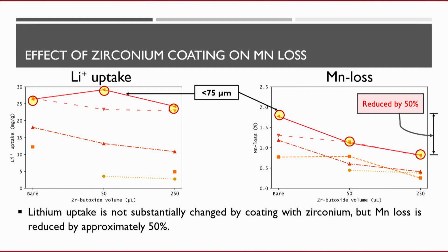Starting on the left, you can see the lithium uptake there, and there are three columns. There's the bare sorbent, the one without any coating. There's 50, which you can think of as a thin coating, and on the far right, 250 is a thicker coating. And the cool thing is, as we raster the thickness of this coating, we don't see any change in lithium uptake. If you go to the right, though, you can see we go from, in this case, about 1.7% loss down to less than 1% loss in each cycle. And so we've reduced the loss by about 50%. We're trying to optimize this because it's critical to be able to reuse these materials at least 100 times for it to be economic.